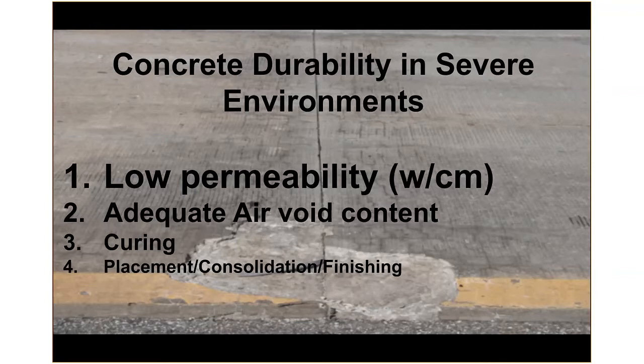screeds on bridge decks, using spud vibrators to get concrete properly consolidated, and then the use of admixtures, water reducers, superplasticizers, and even self-consolidating placements in large beams, columns, things like that, by the use of viscosity modifying admixtures, the next generation of admixtures, VMAs, viscosity modifying admixtures. So you get the concrete to actually self-level and be fully consolidated, especially in structures that contain a lot of steel reinforcement. So, all right, after that primer here, we'll keep going.